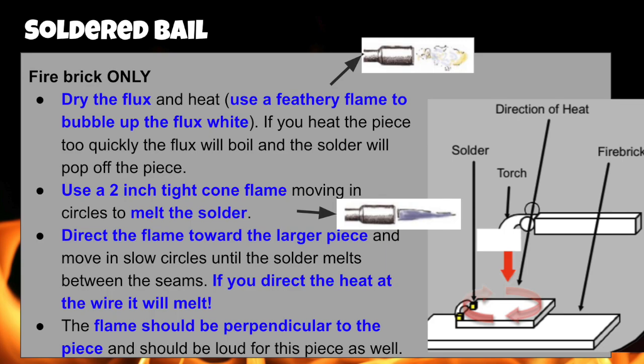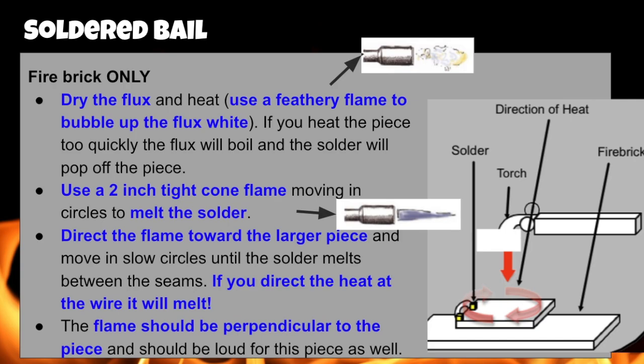If you put too much heat in one area close to the wire, it may melt and you will have to start that part over. You also may have to solder more than once because sometimes one side of the bail will solder and the other side, for a variety of reasons, won't solder. So you'll have to pickle the piece in between, get it set back up, and then try to resolder the other side.